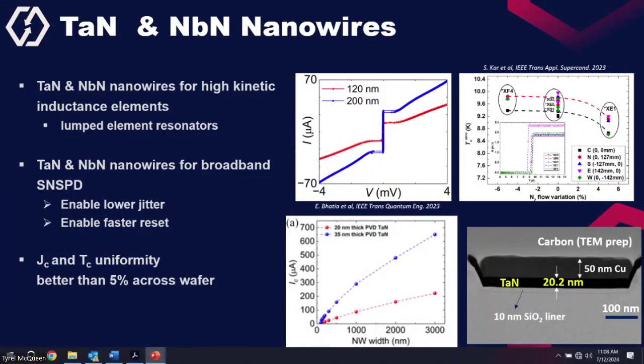Like Pops mentioned about the superconducting nanowire single photon detector, how it detects a single photon. In a superconducting nanowire, below the superconducting transition temperature, we have Cooper pairs. Above the superconducting transition, we have electrons in metals. So when it absorbs a photon, the Cooper pair breaks, and that is how the electronics detects that it has absorbed a photon. But there is some heat dissipation that happens at that time. So if we have this copper on top, which can absorb the heat, it will improve the reset times of those superconducting nanowire single photon detectors. So that is the advantage of using copper.